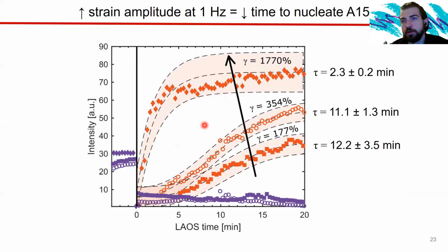So when we investigate the effective strain amplitude at the same frequency, 1 Hertz, you can see that as we increase the strain amplitude, the A15 formation occurs faster. And our Avrami fits hold pretty good. And this was a good result. We were happy to see this.